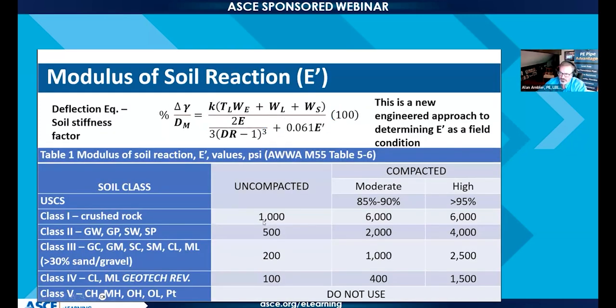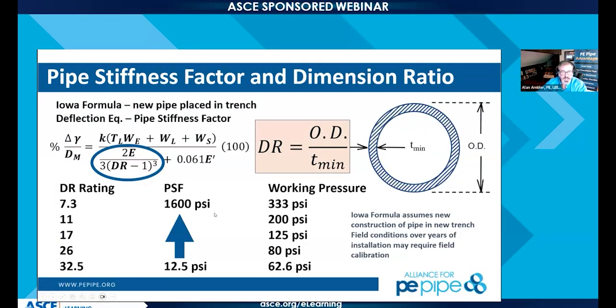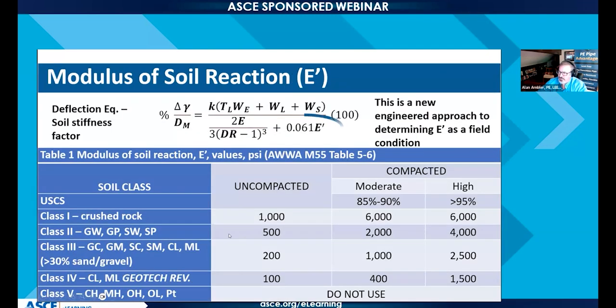Okay. So one of the slides I kind of glossed over here shows us that pipe stiffness factor. So this does work with the exact soil stiffness that Brian was just discussing, and we'll see a fairly dramatic difference between a DR 7.3 and that DR 32.5. So when we start to look at that thinner wall pipe that's outside of that design window we were in reference to earlier, then yes, that engineered backfill gets significantly more important to us as we continue through it.